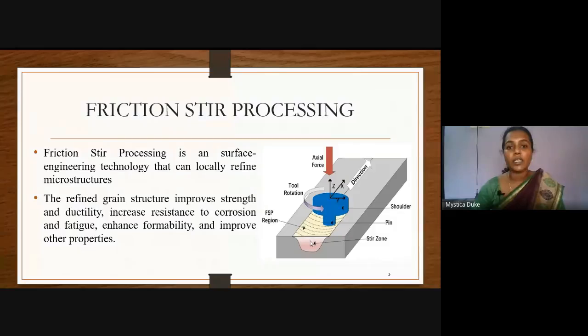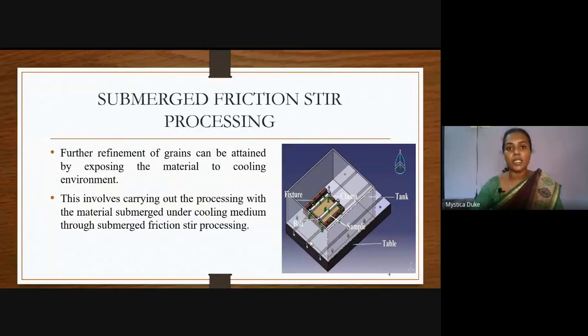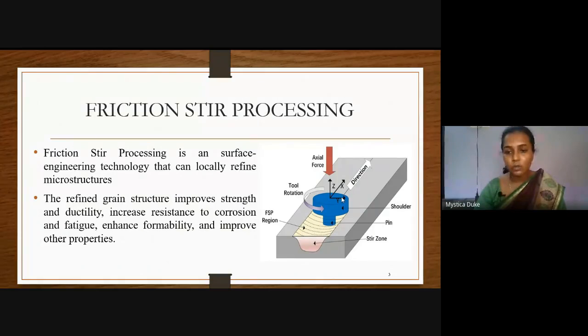We have taken friction stir processing by submerging it in different media. So why do we need submerging in friction stir processing? As I mentioned, as the tool moves, the stir zone is developed, but the heat developed because of the friction is very excessive. This excess heat is sometimes dissipated away from the stir zone into this region, which is the heat affected zone. Because of this heat dissipated away from the zone, the grains in this region tend to be very coarse and act as a point of crack initiation, causing premature failure of the material.